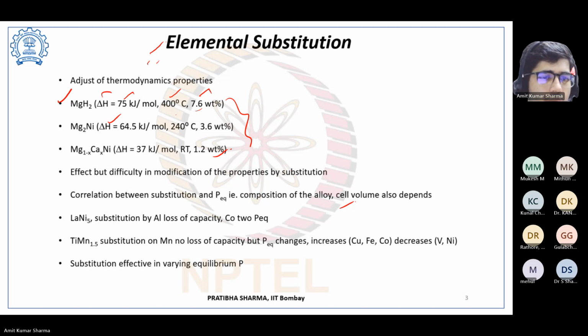So if you have LaNi5 and you substitute with aluminum, you will have loss of capacity. Then TiMn1.5 with substitution on Mn, no loss of capacity. If you replace the Mn, there is no loss of capacity, but P equilibrium changes. So it increases for Cu, Fe and Co. So this substitution is effective in varying equilibrium pressure. So we can do the substitution and change the properties.